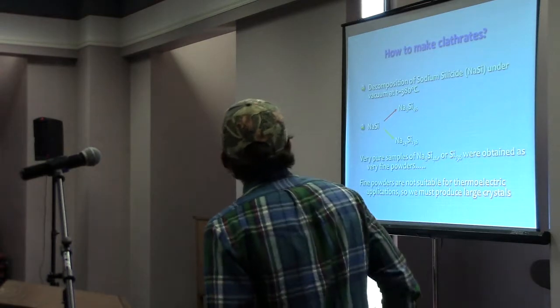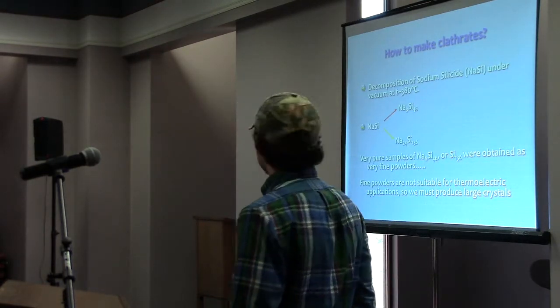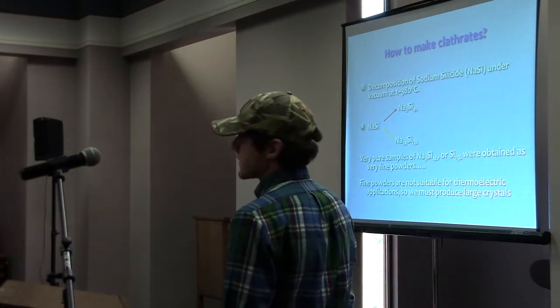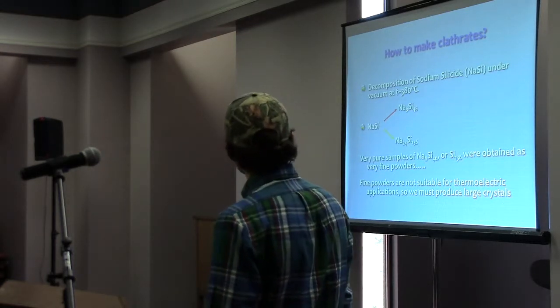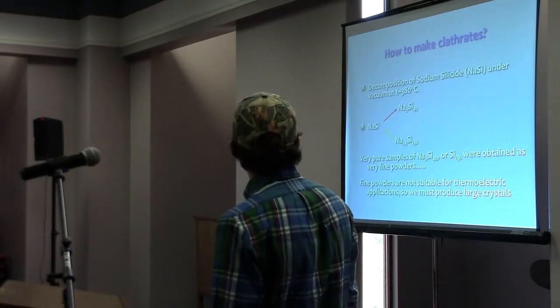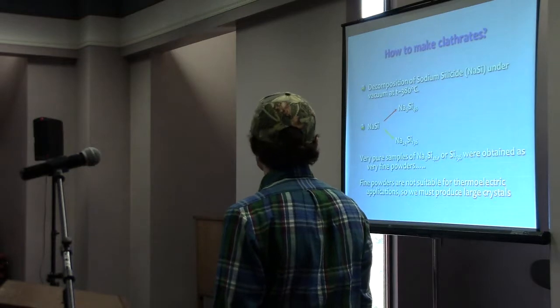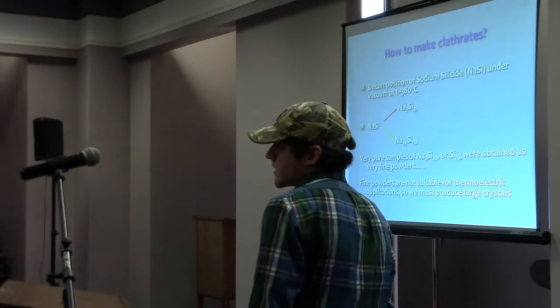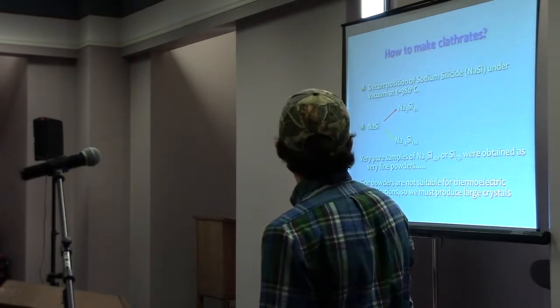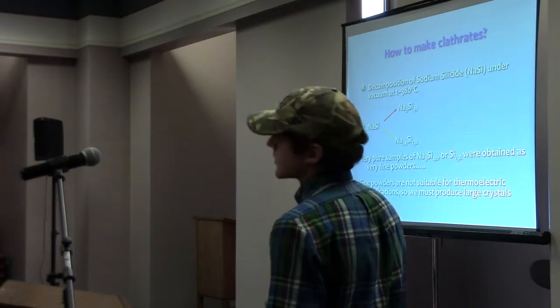And these were made through the decomposition of sodium silicide in vacuum at nearly 380 degrees Celsius, and it decomposed into two products, but we're focusing on silicon-136 clathrate, which is obtained as a very fine powder. But we can't use these powders for any thermoelectric applications, really, so our goal was to produce larger crystals.